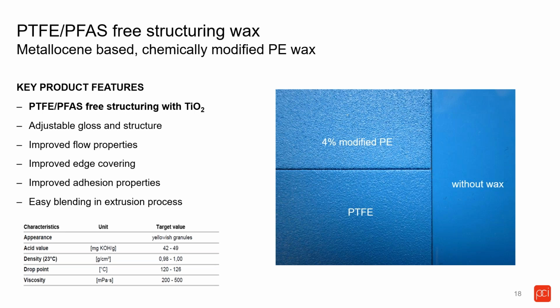And actually, this wax itself is a non-micronized wax, so it would be incorporated pre-grind, pre-extrusion, and then you'd get the particle size that you need after the fact. Of course, I did mention earlier, it stands to reason that the micronized grades are going to typically be more costly just because it's an extra step. So if you don't have to use micronized grades, you're probably better off using a base grade that's a coarse powder.